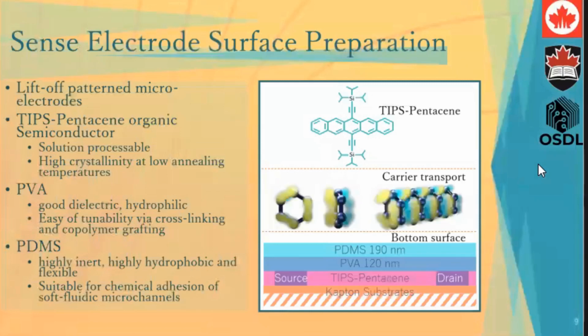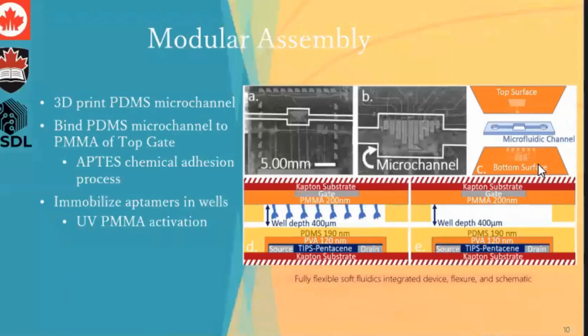We're looking to expand into improving it with a self-assembled monolayer that provides better stability. In terms of the dielectric stack, we have a very thin layer of PDMS for interfacing with the microfluidics. We're using PVA because we have been constantly trying to cross-link into high-K stable thin layers. PVSQ is something that we have looked at, and we are also looking at more biodegradable cross-linking. So we're looking at PVA carrageenan, which is a polysaccharide, but it cross-links really well and gives high-K stable polymer layers, which can be deposited in really thin films. So we have stuck with PVA. We are constantly modifying and improving it, and the TIPS-pentacene creates the channel of the organic electrolyte transistor.